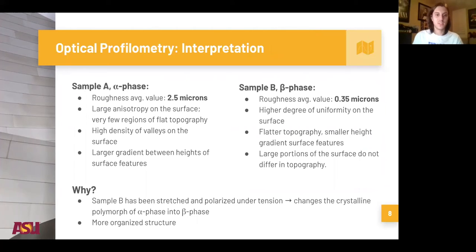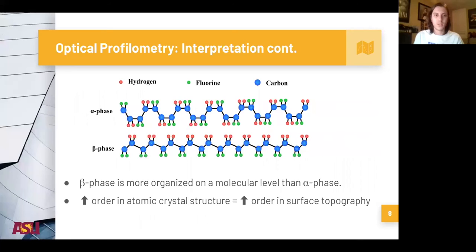The reason for this is that sample B has been stretched and polarized under tension. This is what makes it piezoelectric, and it changes the crystalline polymorph from alpha phase to beta phase, which is much more organized. So this is showing the difference between alpha phase and beta phase. You can see that in beta phase, the fluorine and the hydrogen atoms are oriented in the same way consistently throughout the whole polymer chain, whereas in alpha phase, they're just randomly organized. So we would expect to see a much higher degree of uniformity and less roughness in the beta phase sample, which we did confirm with our results.